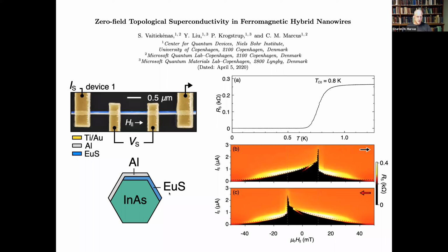Here is a layering of epitaxial europium sulfide grown on the wire, and here are 2 facets of aluminum grown on top of them. The faceting and orientation depends on how you rotate the stage relative to the guns that are putting the stuff on, so you can at will put things on different facets. This happened to be what we put it on for this. And here's what I would like to exhibit first. If you just look at the shell of the device, in other words, let's forget about any kind of tunneling or zero bias peaks or Majoranas or any of that stuff. Let's just look at what's on the outside.